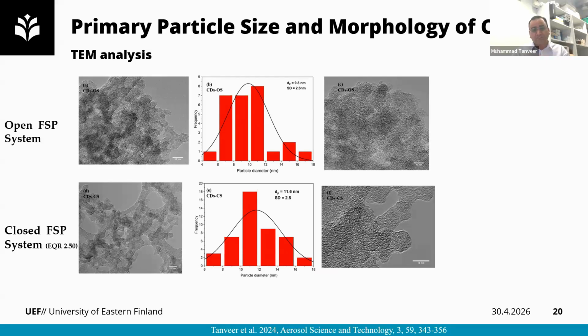But in the case of the closed system, although the particle size is a little bit higher, like 11.6, due to the high temperature residence time in the flame, because when we close the flame, the flame temperature is quite a bit higher, and under high temperature, particles grow further. So that high temperature environment can increase the particle size of the carbon nanostructure, and that's why we get a little bit higher size here. But on the other hand, the morphology is quite good. It's compact agglomerates with some turbostratic structure.